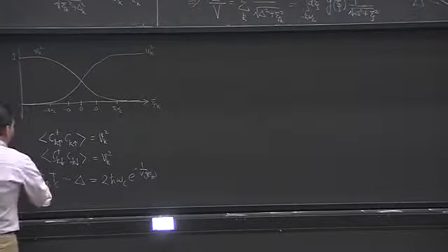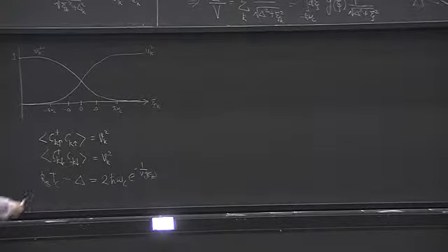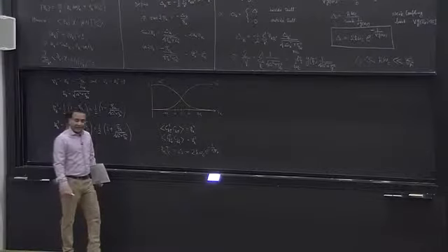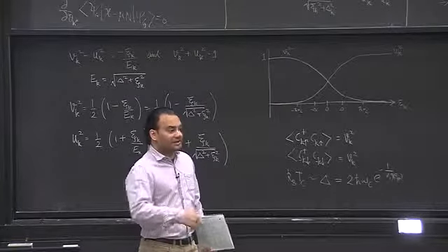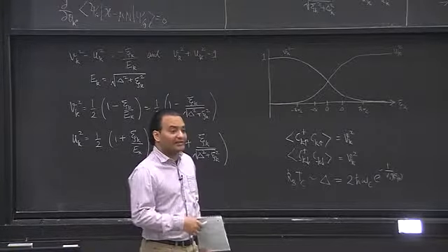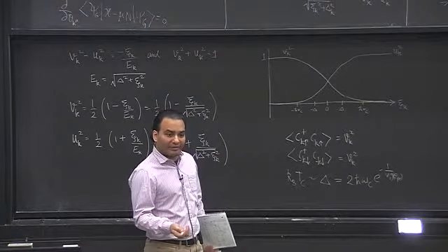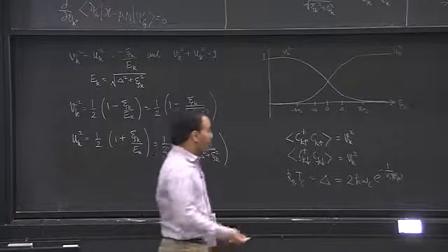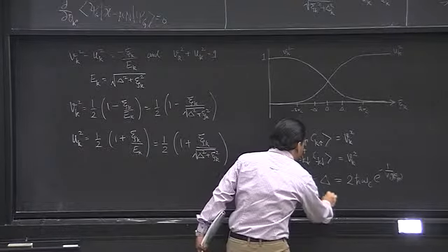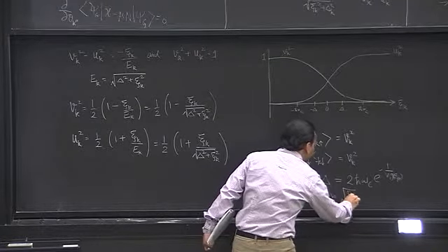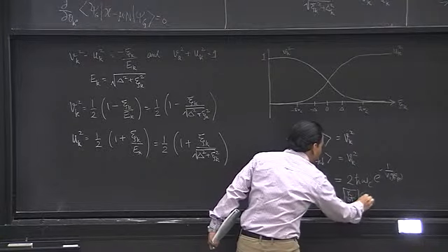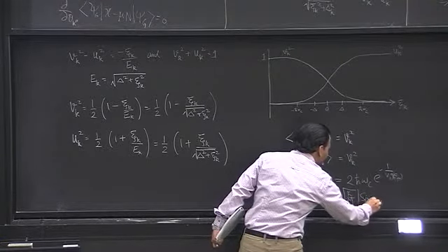Now we can say the following. The transition temperature of a superconductor is related to delta. And this delta depends on omega c. What is omega c? We just discussed that omega c is related to the phonon frequency, or the Debye frequency. It's an energy scale for the phonons. How does the dispersion relation of the phonon look? It goes as the square root of K over M, times mod sine Ka by 2, where K is the spring constant.